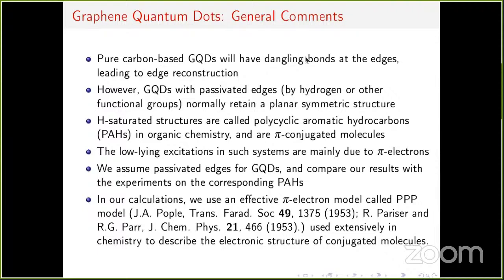Okay, a few general comments about graphene quantum dots. Pure carbon-based graphene quantum dots will have dangling bonds at the edges, which will lead to edge reconstruction. However, quantum dots with edges passivated by hydrogen or some other functional group normally retain a planar symmetric structure. Hydrogen-saturated structures are called polycyclic aromatic hydrocarbons in organic chemistry, and they are essentially pi-conjugated molecules. We all know that the low-lying excitations in such systems are mainly due to pi electrons. Okay, so in our work, we assume that the graphene quantum dots which we consider have passivated edges.